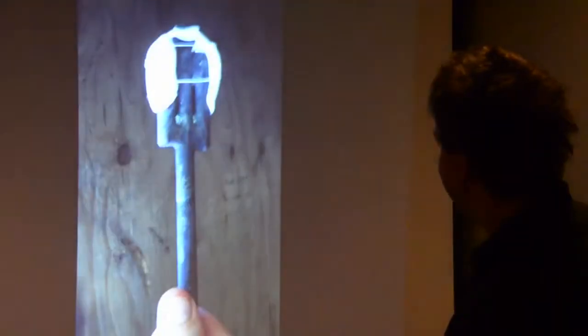stir it. You can use the technique where they add a pumpkin or an apple into the mix, and that'll create gaseous churning of the batch, which is a fine way to do it too. But some of those pigments are really stubborn, and it takes a little extra heat, extra manual stirring to really get them into solution. Once they're in solution, they'll stay that way. So if I have a lot of scrap glass that's colored green, I can throw it back in later, and I won't have to bake another 4 hours. It's pretty easy that way.